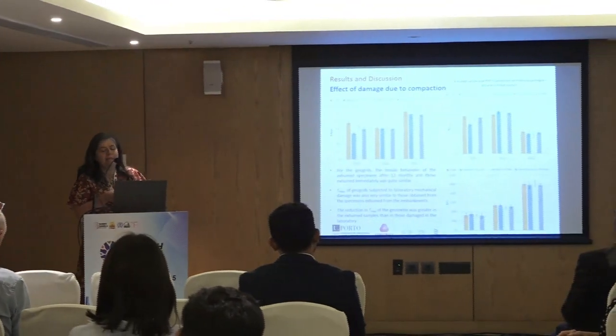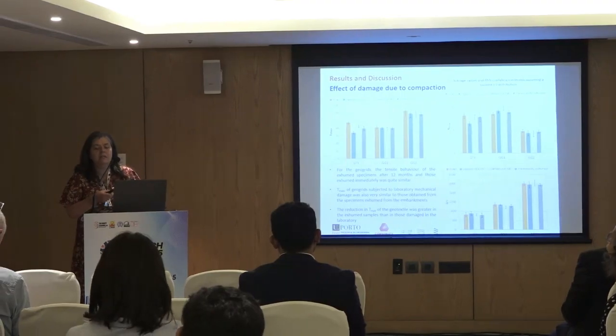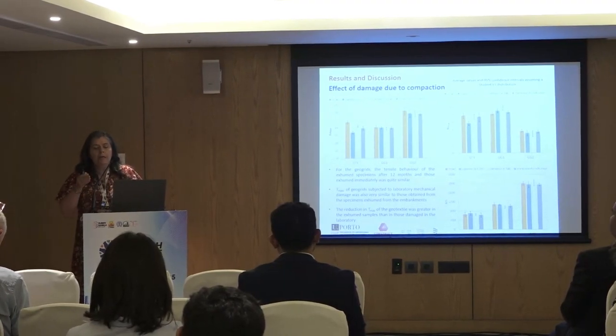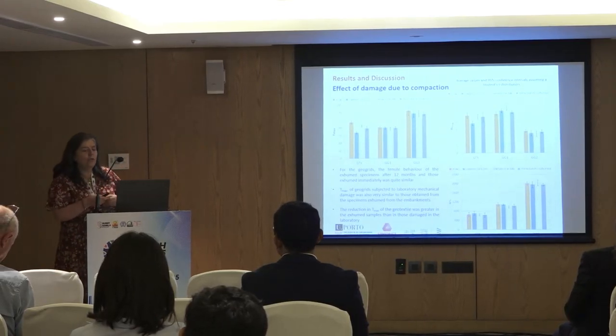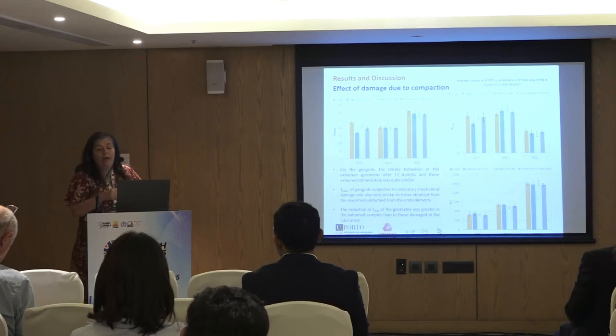I must say that this decrease in the tensile strength of the geotextile is likely associated with some kind of changes in the bonding between the polyester yarns and the non-woven geotextile, induced by the handling and exposure to the fill materials, rather than the direct damage of these yarns. What we can see, particularly in some images, is that the polyester yarns are less aligned, as I mentioned before, and less attached to the non-woven geotextile, which may have contributed to this premature failure.